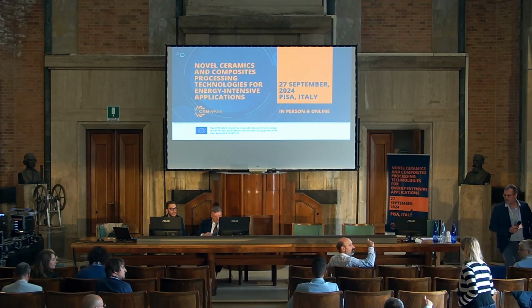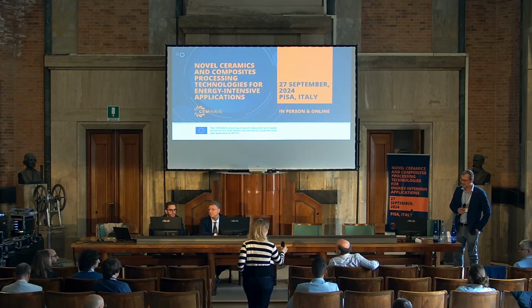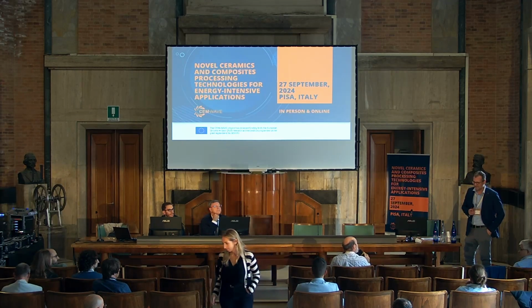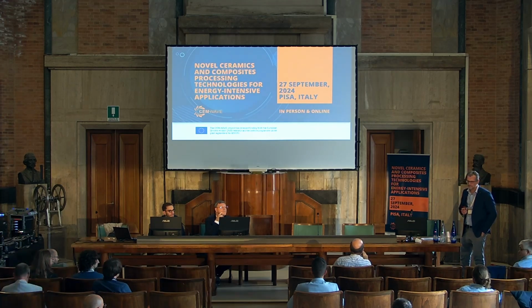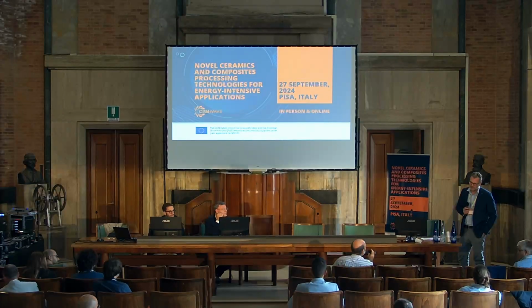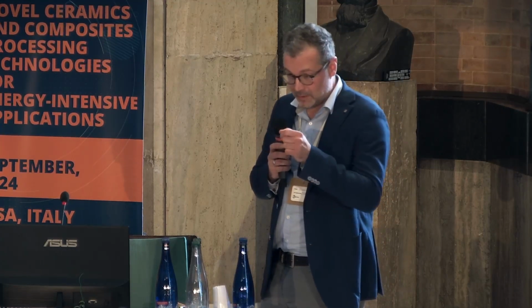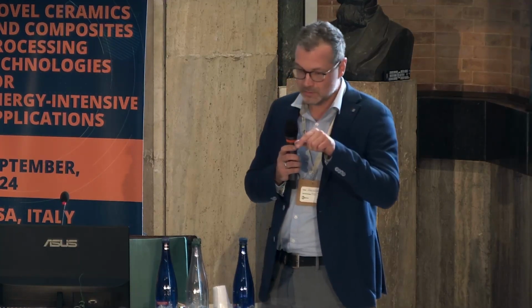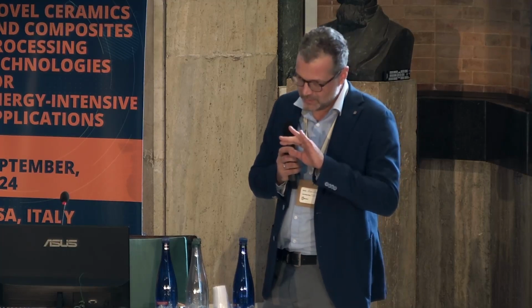Other questions? Thank you for this nice talk. And my question is, you have been systematically using micro-CT for inspection in the end. Do you have other methods such as thermal imaging or whatever, in order to have a somewhat lighter but efficient defect inspection procedure? Right now we used computed tomography with a 60 microns resolution, depending on the scale of the sample. But we could do smaller samples with a high resolution of up to 3 micrometers. We didn't do it yet, but we could do it.